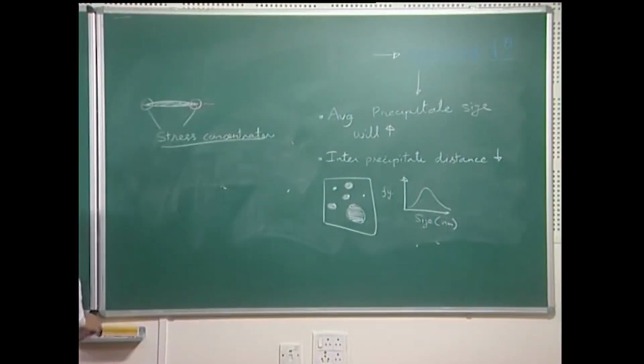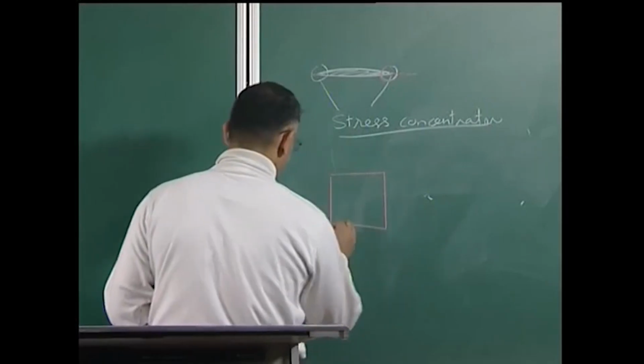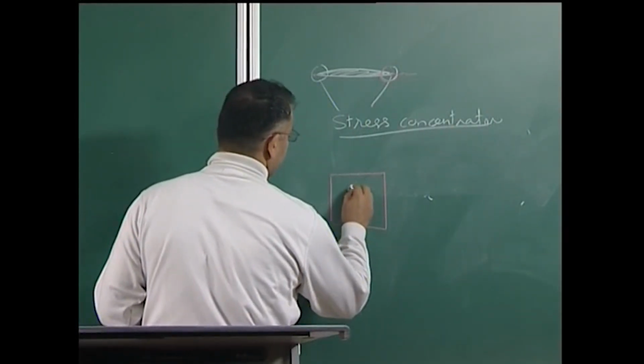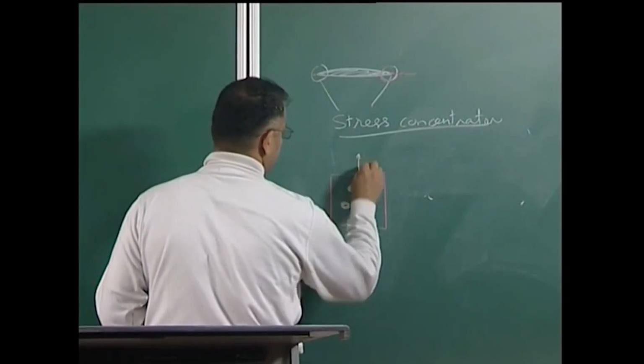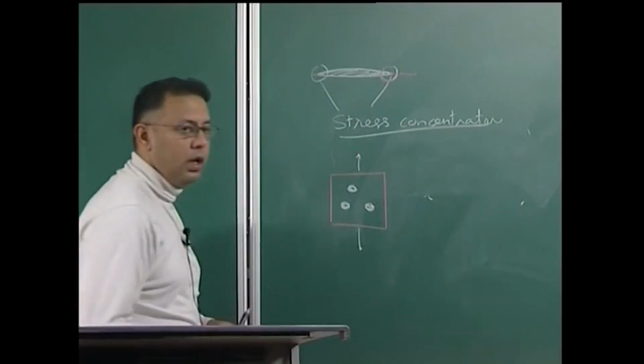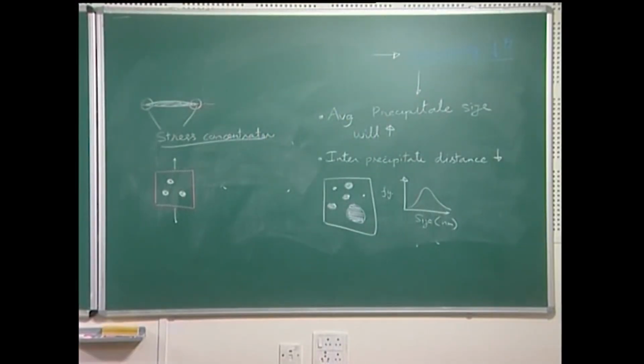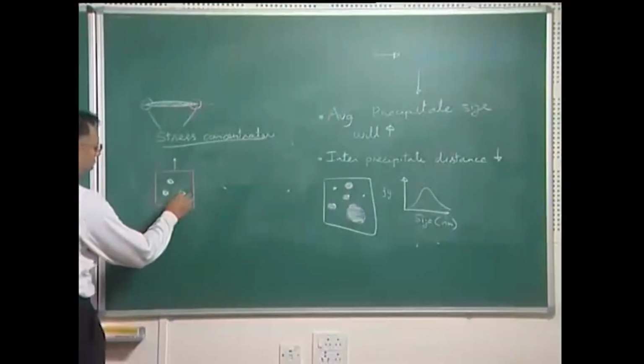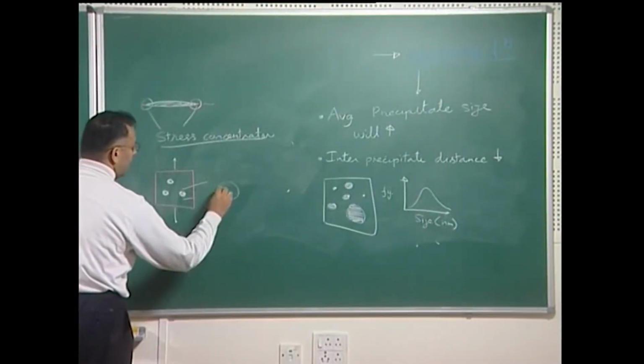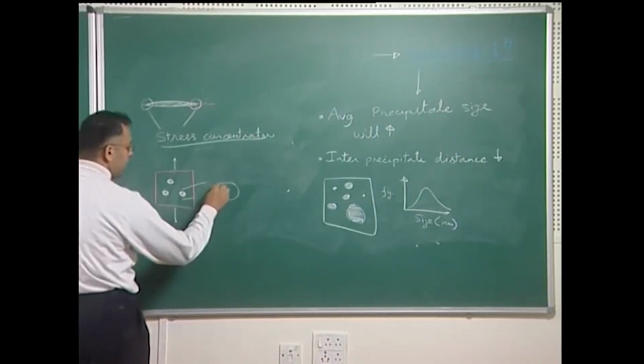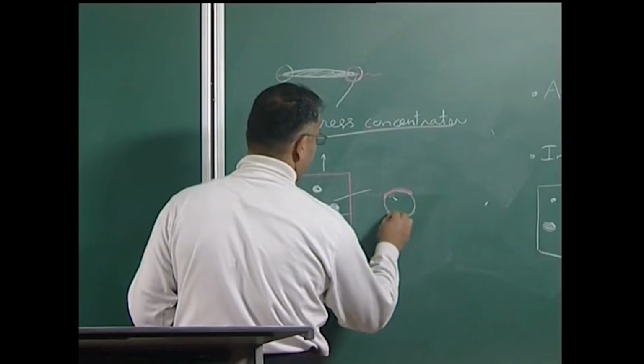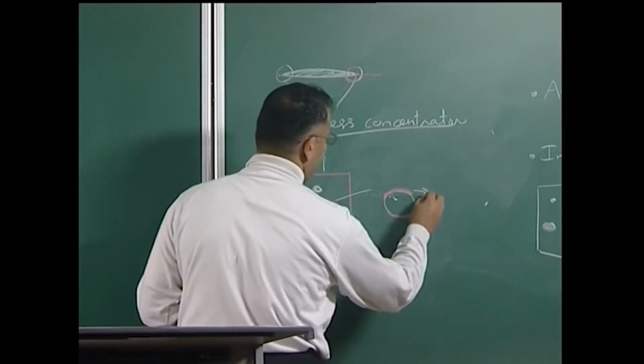But there is one important thing still left out before I can claim that I understand this distribution of phases, which is the interface between the 2 materials. Suppose I am loading such a material which has this distribution of phases. It could so happen that there are no cracks forming in material B, no cracks forming in phase A, but the interfacial bonding is so bad that, let me zoom this part out, an interfacial crack forms. In other words, there is an interfacial debonding because of this loading. This debonded region has been shown in red.